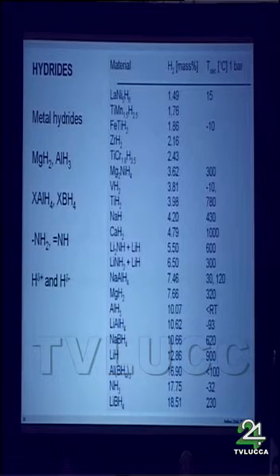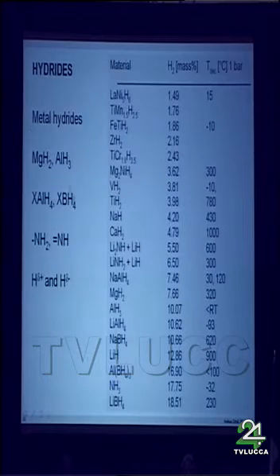And we can put it in another relation with the volumetric hydrogen density, and again there is no relation between the volumetric hydrogen density and the decomposition temperature. So this is a very positive sign, because that means it's not hopeless to look at materials with a very high hydrogen density. They could still work at room temperature if we find the right ones. Now, sorry, that was too fast.